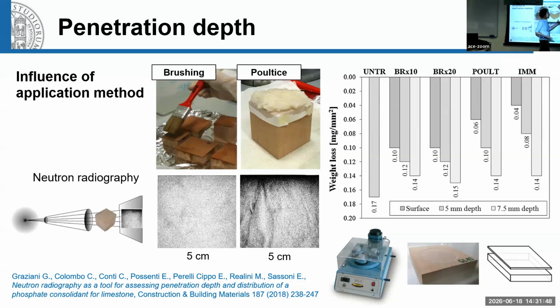This was also confirmed in terms of mechanical properties, for instance, in terms of resistance to abrasion. So we tested how well the material was able to resist an accelerated abrasion test on the surface, and then by cutting some slices from the surface, also at increasing depth down to about 7.5 millimeters from the surface, we found that some mechanical improvement was present. And something good is that the change in properties with depth is gradual, okay? There's not a surface crust and nothing below. There is a continuous, progressive change in properties with depth.